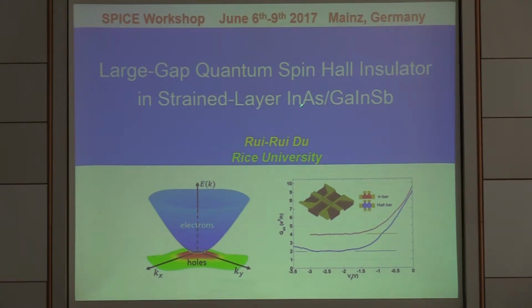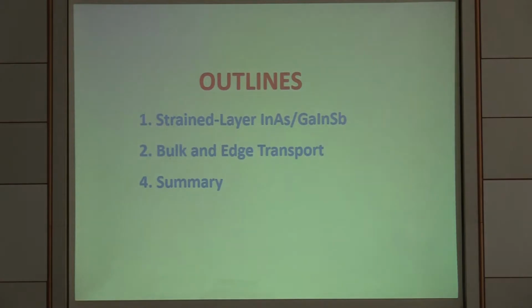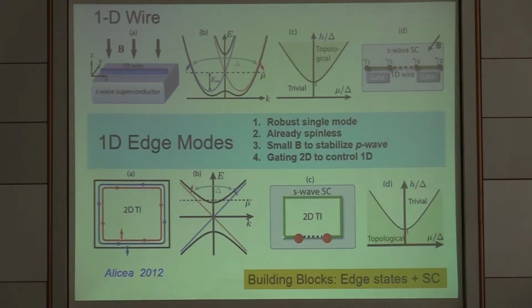So this is the effort to improve the material to make the energy gap, the bulk gap, become larger. Of course, not as large as room temperature, but much larger compared to the previous material, indium arsenide gallium antimony, by an order of magnitude. Because this is a short talk, I will just talk about two parts. First, what is strained layer indium arsenide gallium antimony? And second, what are the properties of those materials.